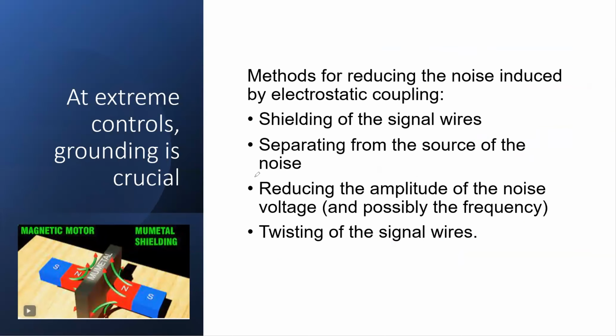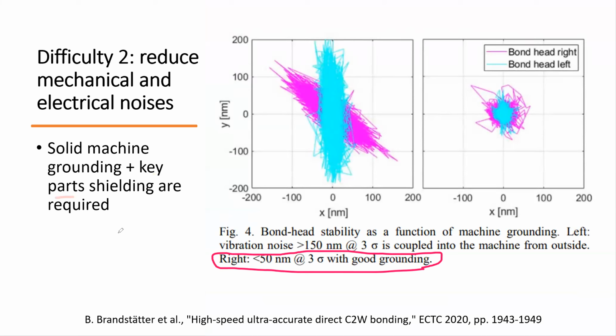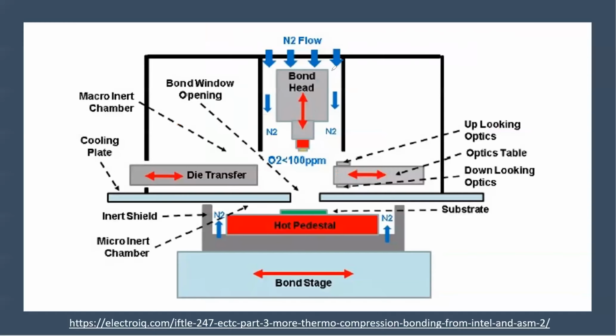And if you look at all these shielding techniques in a textbook and online, there's mu-metal, which is blocking the magnetic field. So this component will not touch that, will not affect the other component. Mu-metal is a special alloy that will actually absorb all the magnetic fields that are going through it. So you need shielding of the signal wire in a separate source from the noise, reducing the amplitude and then twisting the signal wires. These are simple things, but there is actually more than this. There are some delicate things that every vendor knows about their tools, that they do specific twists to make sure their tools are grounding well. And then the key components inside will show it. So when they have a delicate motion of forcing this plate down, it will not be affected by the noise that comes from the system.